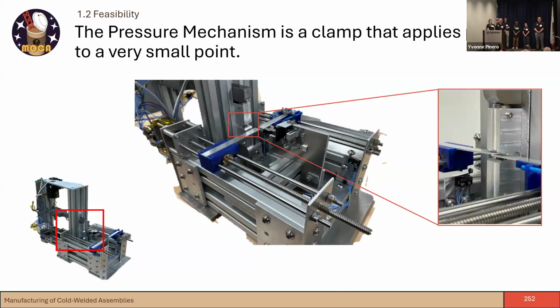And here we can see a little bit of a close-up where the action actually happens, the crimper head. It's between the two vertical extrusions there. What that contains is two pins that press down on the overlapping samples in such a way as to cause enough plastic deformation that you get atomic diffusion, where the metal atoms actually pass through each other, even if there's a little bit of some oxides left over on the surface. And that jaw right there is where the samples actually slide into for that pressure application to happen.